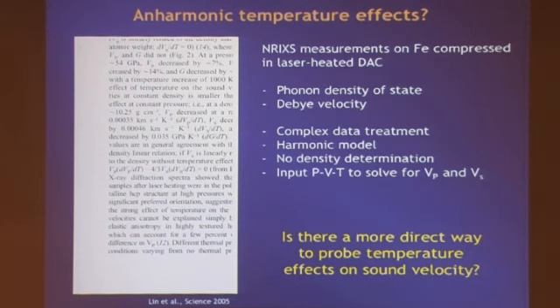Anharmonic high temperature effects were suggested, in a figure that is not plotted here, by nuclear resonant and inelastic X-ray measurement performed on laser heated sample. This time the sample is compressed into a diamond anvil cell and heated by two laser beams. This is the technique I was describing before, where the phonon density of state was measured and then the velocity. This technique indicated a softening, at constant density, both for VP and VS.